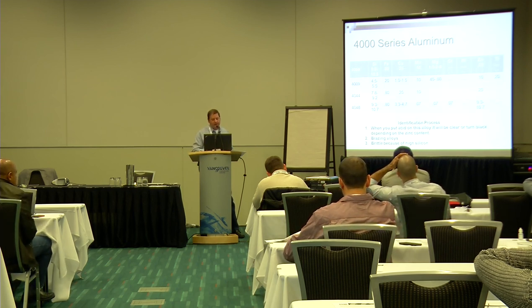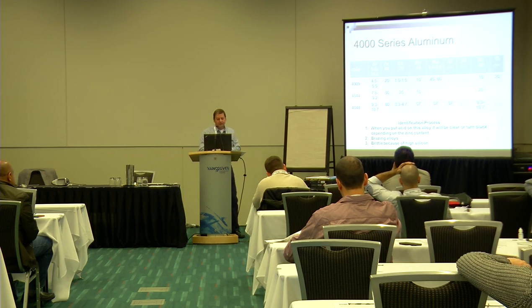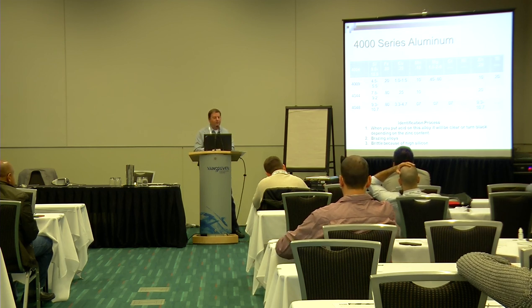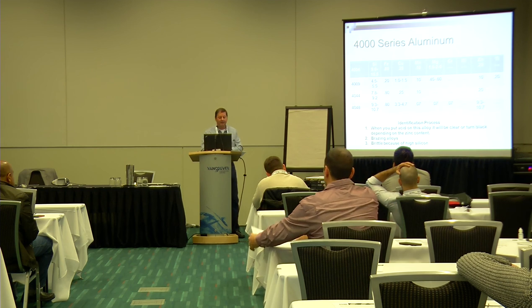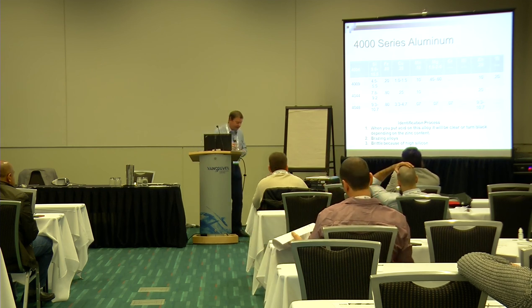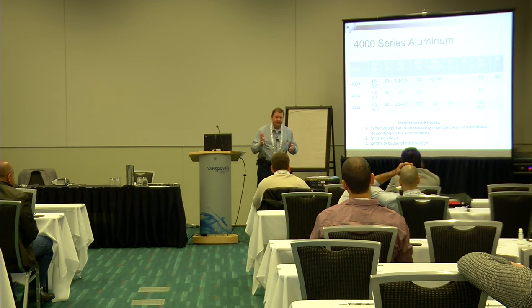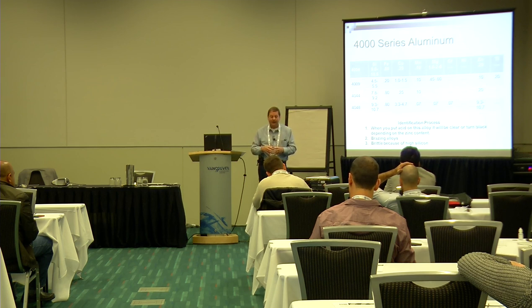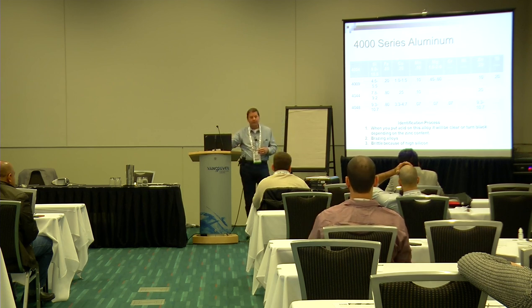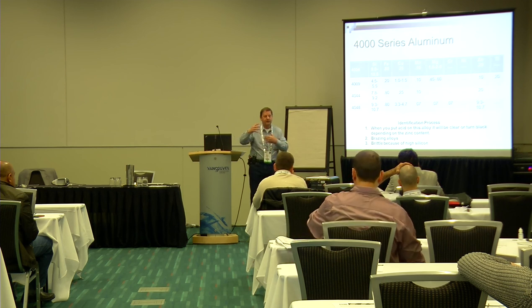4000 series. Look at your silicon. You look at 4004: silicon's 9 to 10.5. A lot of silicon there. The reason you look at that is that we use a lot of silicon, and all our alloys on our casting side use anywhere from 6 to 12% silicon. If I'm buying silicon in the open market just by itself, the range could be $1.40 a pound. But if I can pick it up in some of this scrap, I don't have to use it. I can replace it.